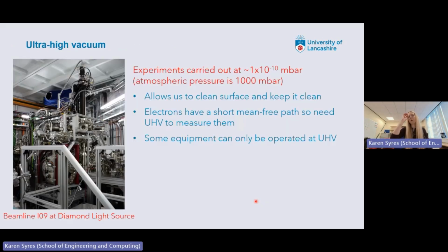When we look at surfaces, we tend to carry out these measurements in what's called ultra high vacuum. Atmospheric pressure is 1,000 millibar, if we're using millibar as the unit of pressure. We do our experiments at about 1 × 10⁻¹⁰ millibar. So that's like 13 orders of magnitude difference.